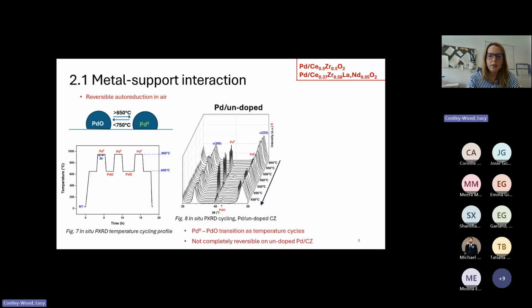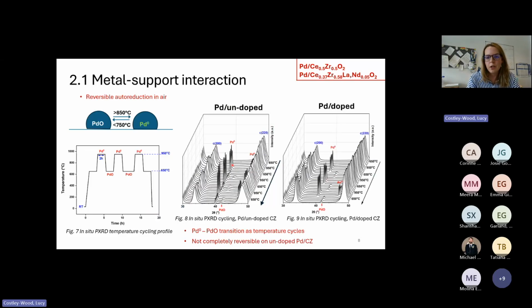If we look at the results for the undoped material, so this is just palladium on the 50-50 ceria zirconia, we see reflections from palladium metal present at high temperatures, and then some very small broad reflections from palladium oxide present at low temperatures. But crucially, we have some palladium metal left over at the lower temperatures. If we compare this now to the doped material, you see the absence of any reflections here, meaning that apparently all of our palladium metal has reoxidized at this lower temperature. What can we infer from this?